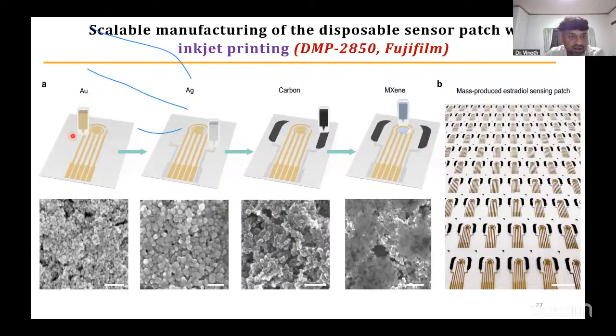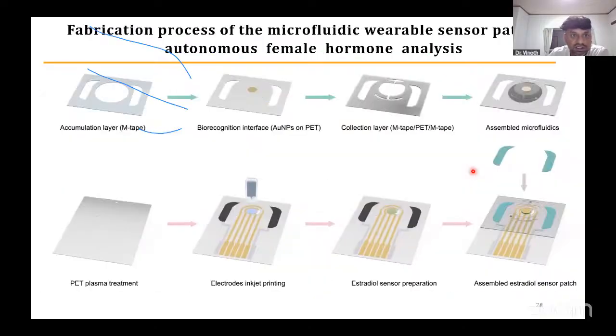Here, first we print gold, then silver, and then silver and carbon for the counter electrode. This is mass production on an A4 sheet. Usually, commercially, we use an OHP sheet, and we are using the same OHP sheet as the substrate. This is the fabrication of the microfluidic wearable badge from the PET sheet. A PET sheet is an OHP sheet.